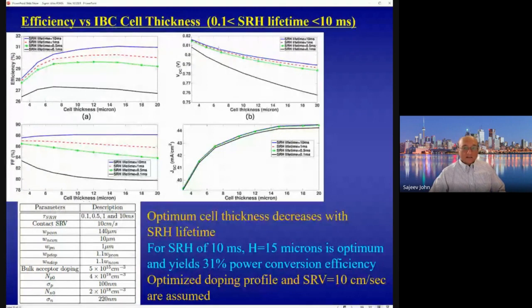And if you now make the quality of the silicon lower, the optimum thickness becomes smaller. As you come down to the worst quality silicon, this black curve here, with a lifetime of only 0.1 milliseconds, the optimum thickness is now down to 7 microns. But even then, the predicted efficiency is slightly over 27%, which suggests that a 7 micron thick structure consisting of polycrystalline silicon could achieve this unprecedented world record type of efficiency. And so here again, we've assumed a surface recombination velocity of 10 centimeters per second. If you were to increase that surface recombination from that value, these efficiencies would get much worse than the predictions that have been made here.